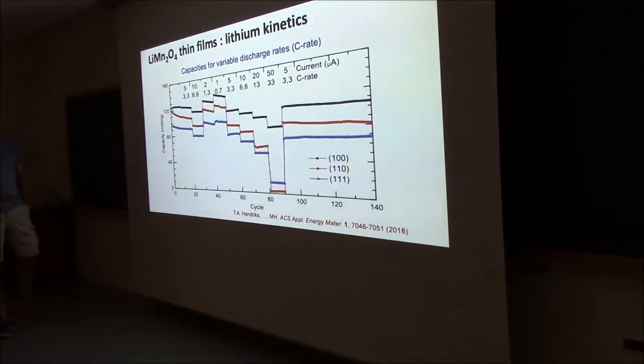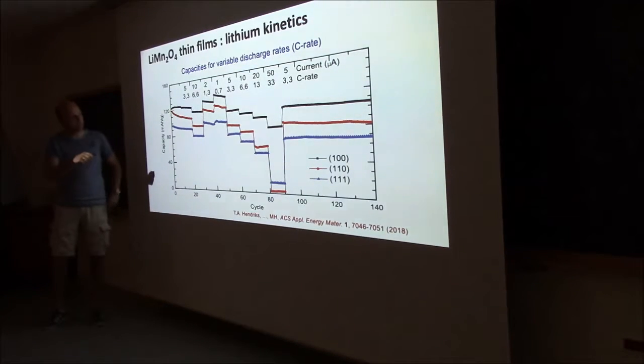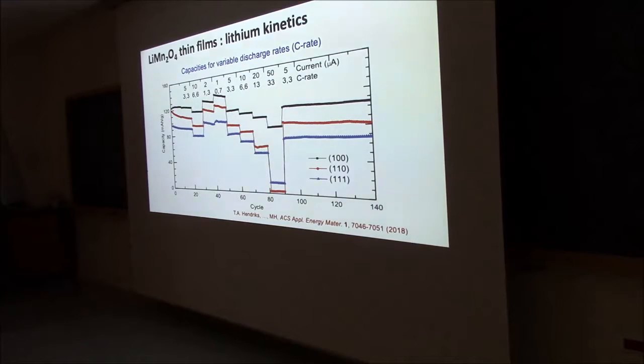So if we cycle these lithium manganese oxides for, let's say, over 100 times, and you vary the C rate, so the current at which you do that, you can see the capacity which you're pulling out is high if you do it slowly, and it's going down if you do it faster. This is a little bit slower again, and then faster is going down, and then you bring it back up. So from beginning to end, it decreased a little bit because you went through a range where you did it reasonably fast. But what you can see here is that when you try to do it 10 times faster than normally, when you have the 100 orientation, you still have a significant amount of capacity, where in the 2 other orientations, this is not there anymore.